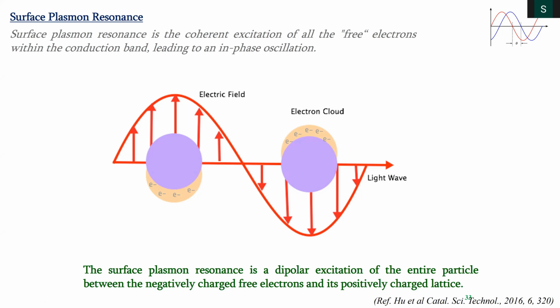that energy then gets converted into either heat, the loss being thermal energy, or that energy then excites the electron in the Fermi level, and the electron goes to the excited state. We call them energetic electrons or hot electrons. Now one can use these hot electrons in the gold, transfer them to a CO2 to get a CO2 radical anion, and those are very active species to react with. Or one can use the heat that is produced to carry out thermal catalysis. And so that's what we wanted to use.